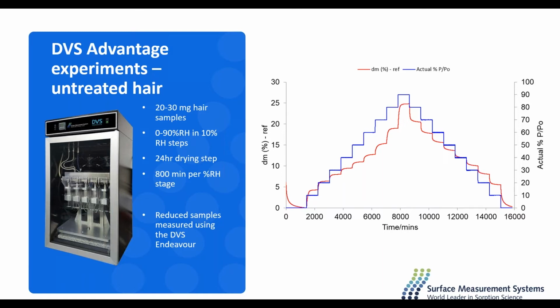So for each experiment, about 20 to 30 milligrams of hair was used, as it does absorb quite a lot of water. We took our isotherm from 0 to 90% relative humidity in 10% relative humidity steps. We included a 24-hour drying step to really make sure we'd removed any ambient water. Now, normally DVS experiments use what's called a dm/dt mode, where a certain change of mass is detected, and then the relative humidity stage will proceed to the next relative humidity step.